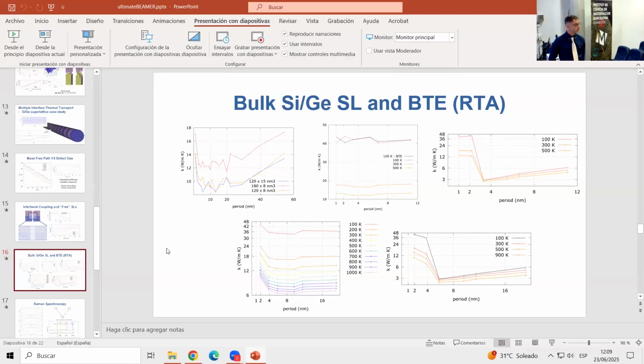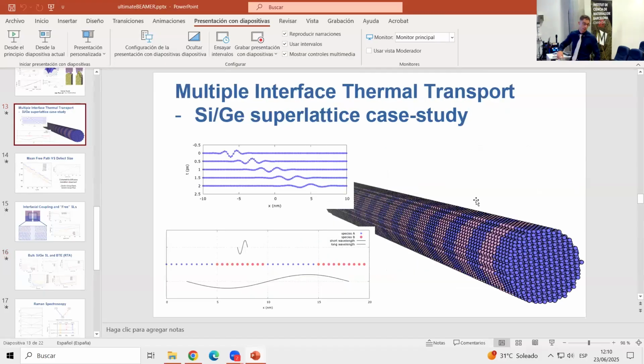Also, I guess that when you simulate the nanowire, you also need boundary conditions for the free surfaces, right? When it comes to the nanowire, we haven't simulated the nanowire using the BTE. The BTE was only about the bulk. We only simulated the nanowire using molecular dynamics. Okay, and of course, here you don't have any boundary condition in the cross plane.